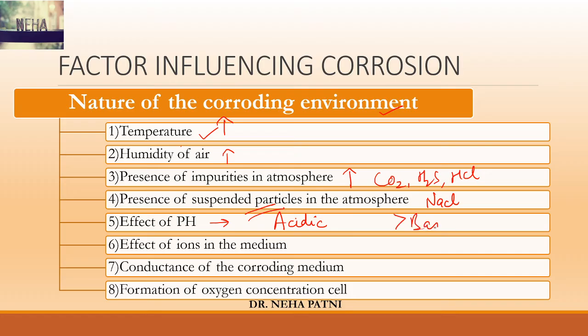Effect of ions in the medium depends on the nature of ions present. If silicate is present in the medium, it leads to the formation of an insoluble reaction product — for example, silica gel — which inhibits further corrosion. On the other hand, if chloride ions are present in the medium, they destroy the protective layer, thereby exposing the metal again to the atmosphere, which increases corrosion.